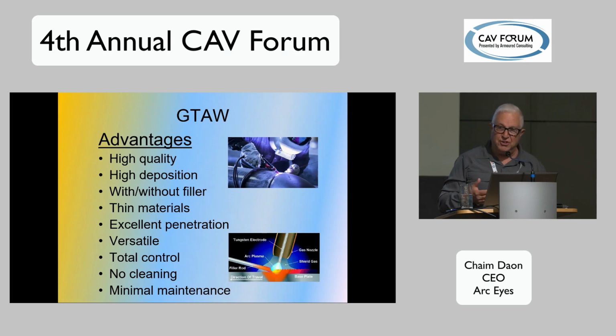So here we have high deposition. For thin materials, we can weld with or without filler metal. For example, very thin material, 1 millimeter thick, we don't need filler material because the arc will just fuse the metal together. We have excellent penetration.